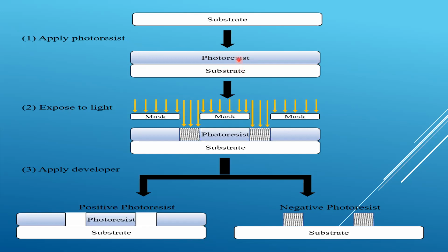After placing it, we heat this combination of photoresist and substrate, generally at 115 degrees centigrade for 1 minute. After heating, a solid layer of the liquid polymer, which is photoresist, will accumulate on the surface of the substrate. Now, the photoresist film has been developed on the surface of the substrate.